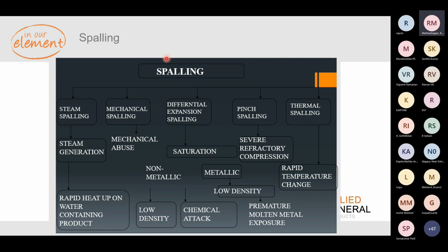As I said before, the moisture in the system has to be removed properly before the working lining is done. So that's the reason we recommend you to follow the GLD values or the moisture meter values to ensure the complete moisture has been removed from the system. Normally, it's very less seen in coreless furnaces, but it is largely seen in ladles and pressure pours and tundishes, where we engage with castables. So that is one thing.